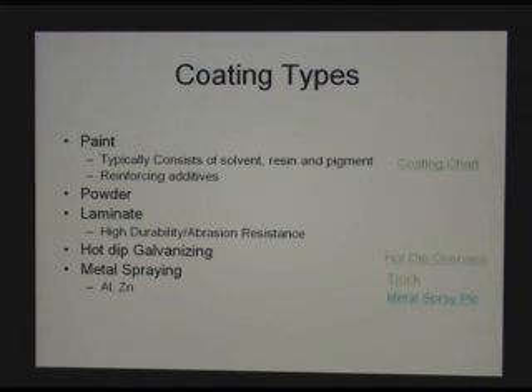Recently we got involved in powder coatings, which are typically used only in factories normally, but our client is in North Slope. He wants us now to use powder coatings under insulation, in the piping, which is a fusion bonded epoxy in this case, but there are many other chemicals that can be used as powder coatings. There are laminates, which is a combination of a regular paint reinforced with fiberglass, either chopped fiber or a fiber mat. These coatings are pretty thick, durable, and abrasion resistant.